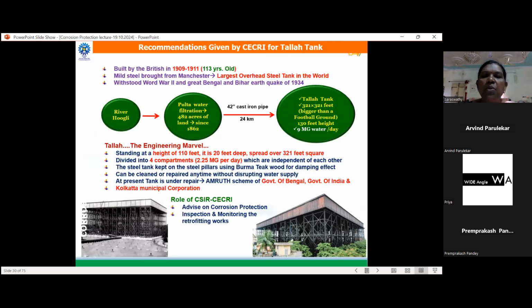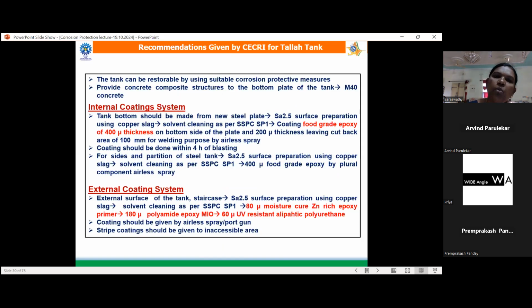Another important structure is the Talla tank, which was constructed during the British period, and recently it had some corrosion issues. They approached us, but the strengthening of the structure was done by the government of Bengal and the nearby engineering college. We recommended using food grade epoxy internally, and externally we advised them to use zinc rich epoxy primer, polyamide epoxy, and UV resistant aliphatic polyurethane for the external surface. For the internal surface, we recommended food grade epoxy, since it is used for drinking water purposes.